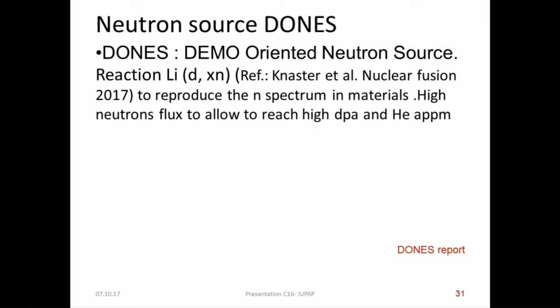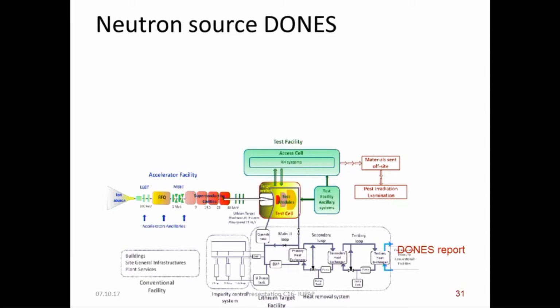And this is done through the reaction of lithium with a deuterium beam of about 40 MeV, and then it can produce a certain number of neutrons. And the principle is relatively simple. You have an accelerator of deuterium, 40 MeV, which falls into a liquid metal target and produces the neutrons, which have roughly the acceptable spectrum for our need of testing the material under 14 MeV neutrons.